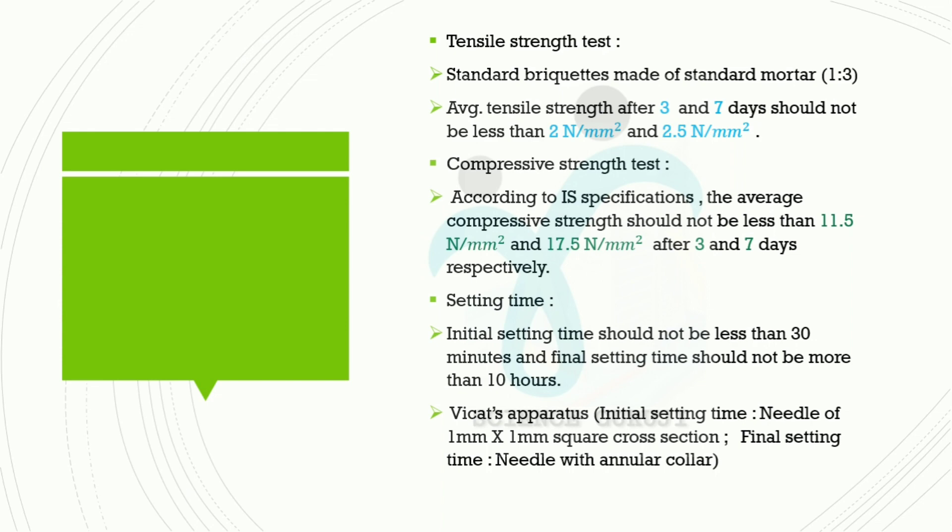Next is setting time. Initial setting time should not be less than 30 minutes and final setting time should not be more than 10 hours.